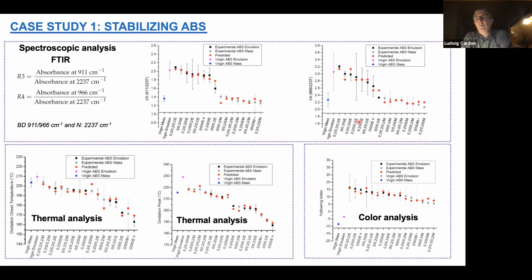When you buy ABS as a virgin material, a lot of times these materials have already been stabilized, especially in the scope of oxidation. But we noticed ourselves that when you use them one time, the original pellets are not always the same as after one processing. So in this investigation, we combined spectroscopic analysis and FTIR, thermal analysis technologies, and color. So we identified the yellowing during or after processing.